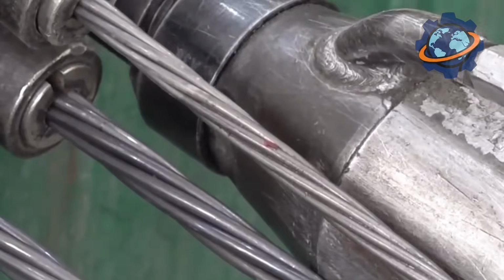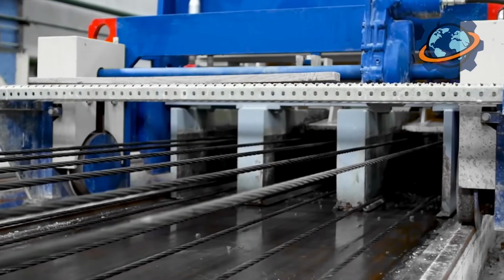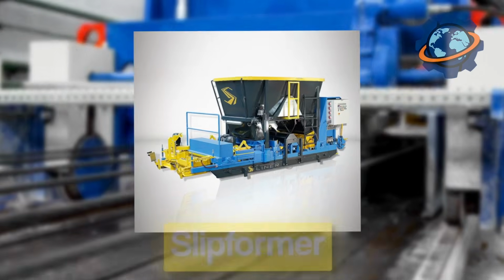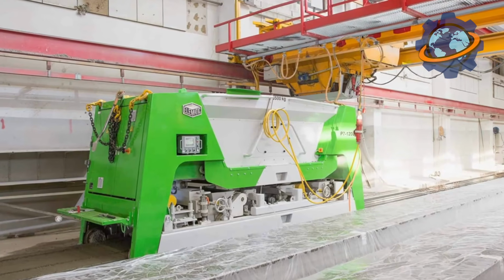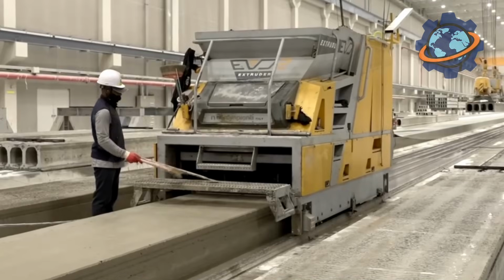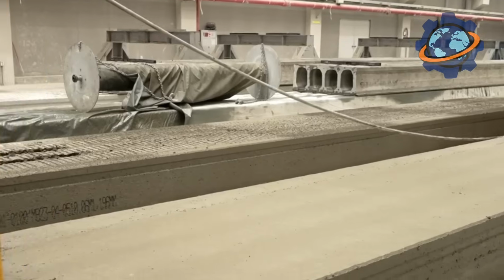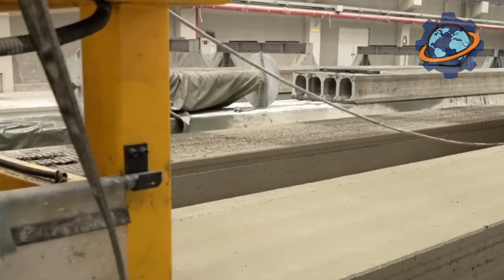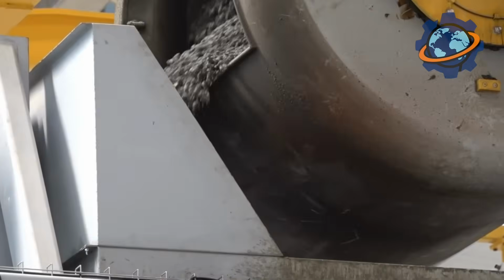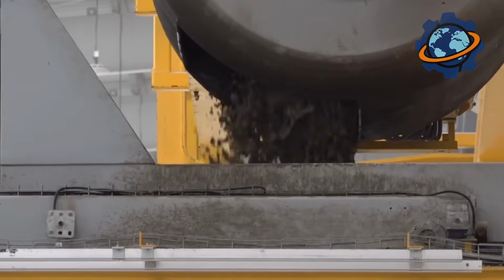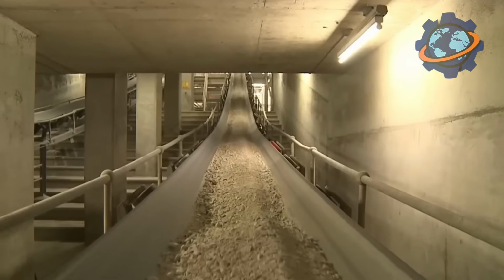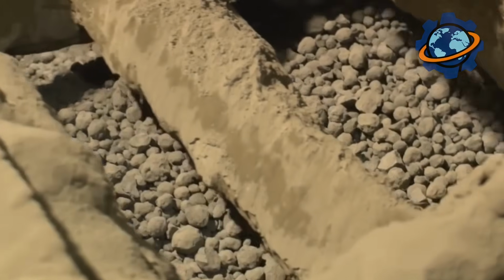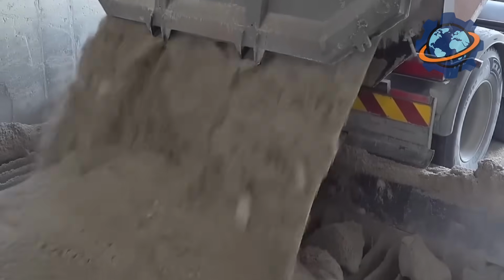When the steel skeleton is strained and singing with tension, the star of the show appears, the slip former. This is one of the most incredible machines in the construction world. Imagine a strange, low-slung, self-propelled creature, slowly crawling on rails along our long bed. It has a large hopper on top, which is filled with concrete. But this isn't your typical liquid concrete. It's what's known as zero-slump concrete. It's so dry it looks like damp earth. If you picked it up, it wouldn't flow through your fingers.